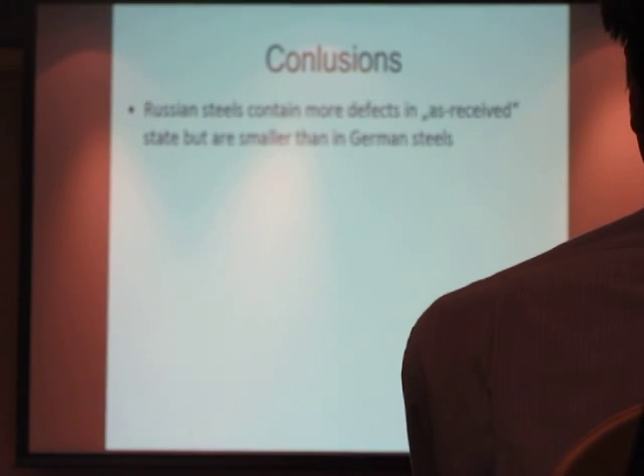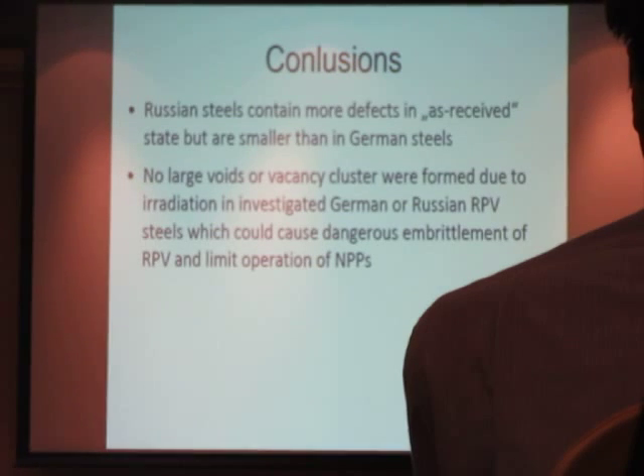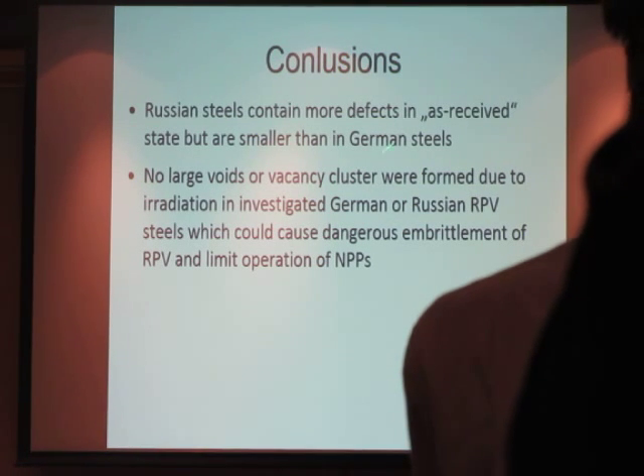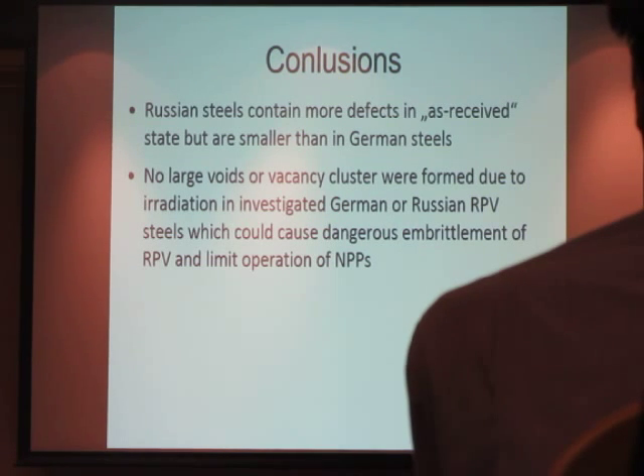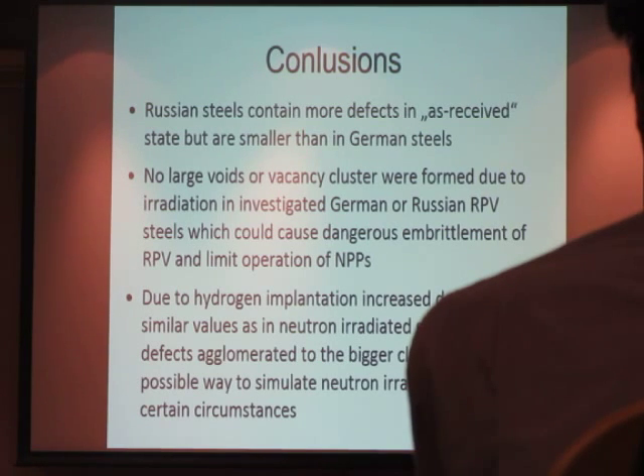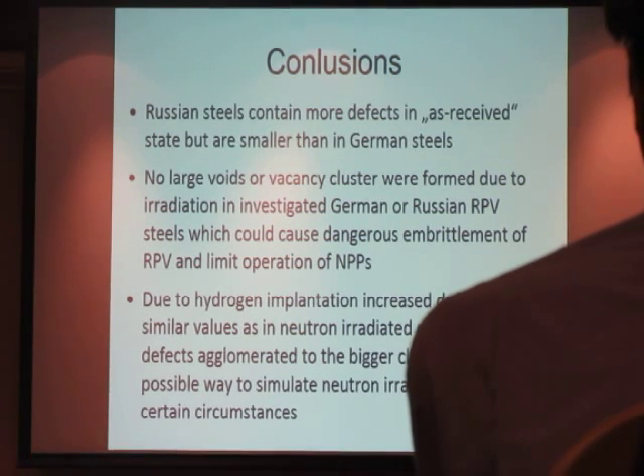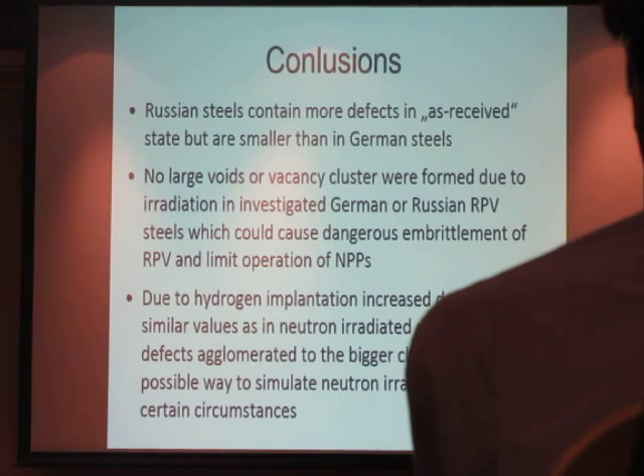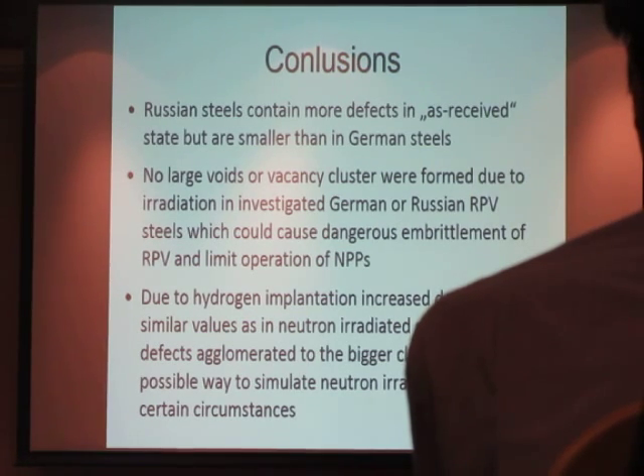So, to conclude, the defects in the Russian case were smaller, no large voids. It means there are no large voids or vacancy clusters, which is important for the regulatory authority to agree, but the decision is not made according to positron annihilation. The decision is made according to notch tests and Charpy tests. It's only additional information. Due to hydrogen implantation, defect size increased to similar values as in neutron irradiated specimens and defects accumulated into bigger clusters. It is a possible way to simulate neutron irradiation under certain circumstances. And that's all from my side. Thank you for your attention.